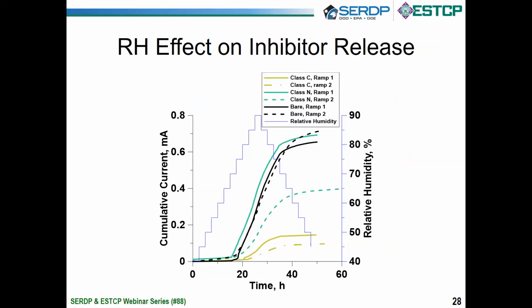Okay, so again, corrosion morphology is affected by the time we spend in each of these humidity regimes, above deliquescence and below. This is some work that was performed by one of my colleagues, Eric Amaka, here at Southwest Research Institute. I mentioned to you before those multi-electrodes, and this is the data, and instead of tape over those top hats, we had coating. The idea was that we'd expose these to chambers, we'd leach inhibitors out, and either protect or not protect electrodes.